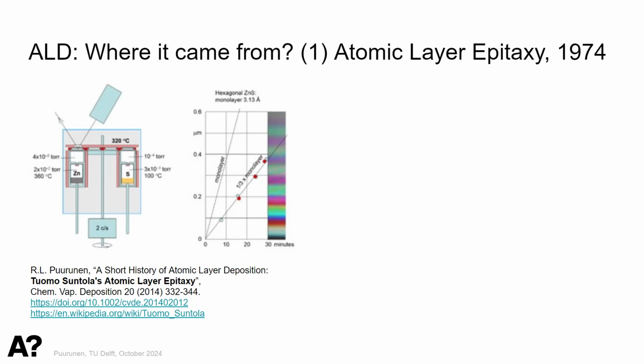And he wanted to make electroluminescent displays working on high voltage to create the light. He started with zinc sulfide films. The first process was based on elements as reactants, just zinc and sulfur. He built a reactor where they were heated, zinc up to 360 degrees and sulfur to 100 degrees. And it was a rotary reactor where a glass substrate was rotated between these chambers.